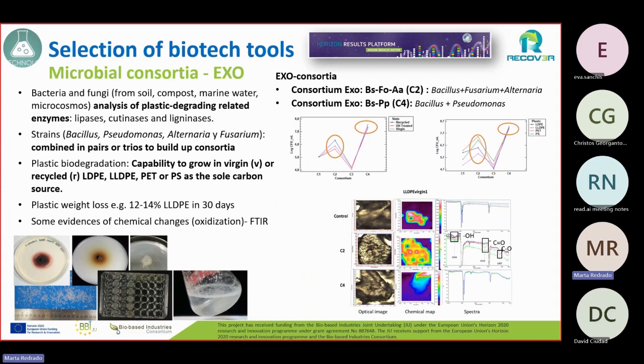The plastic degradation was analyzed through the capacity of the consortia to grow on the plastic. We tested all the plastic we selected at the beginning, the 4 types of plastic, in recycled and also in virgin form. When the microorganisms are capable of growing on the plastic as the sole carbon source with no other nutrients, we consider that this consortium may be successful. Together with this, we also analyzed the plastic weight loss. In fact, we obtained weight loss of LDPE between 12 and 14%, which is quite a lot, but in 30 days, quite a long time as well. Here you have 2 of the consortia that we then worked with in different experiments.